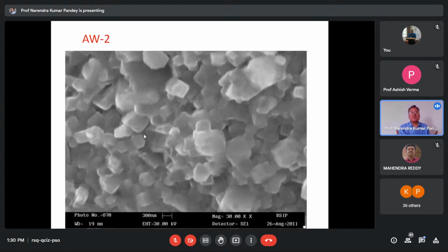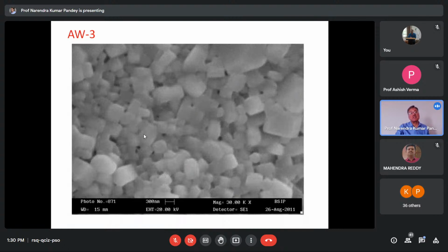Then for 2%, you can see how the crystals are clearly visible. Then for 3%, you can see the crystallites are very, very visible over here. And you can see the small range that we are seeing over here from here to here is 300 nanometers. So the crystallites are very, very small to slightly larger also. And here the magnification is, you can see, 30,000 times.